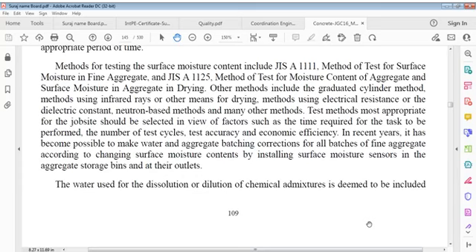Test methods most appropriate for job site should be selected in view of factors such as time required for tasks to be performed, number of test cycles, test accuracy, and economic efficiency. In recent years, it has become possible to make water and aggregate batching corrections for all batches of fine aggregate according to changing surface moisture contents by installing surface moisture sensors in aggregate storage bins and at their outlets.